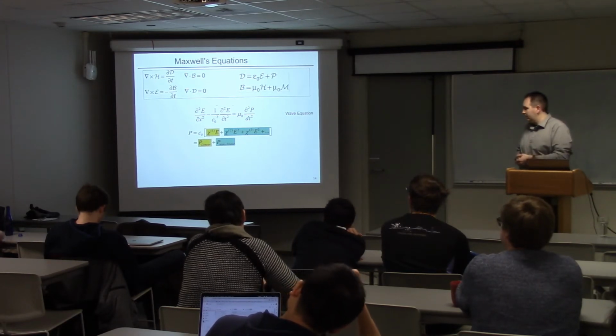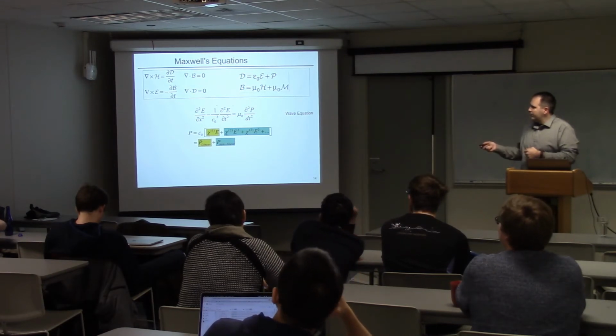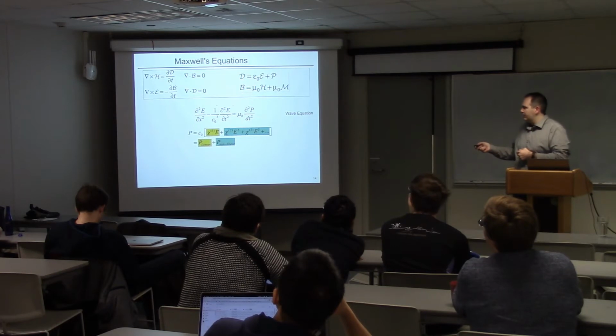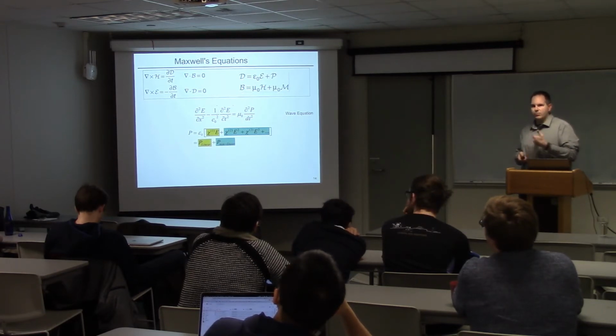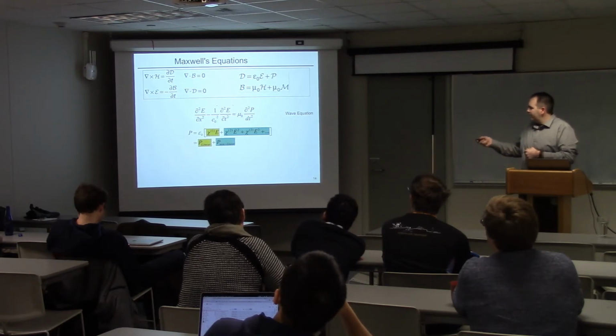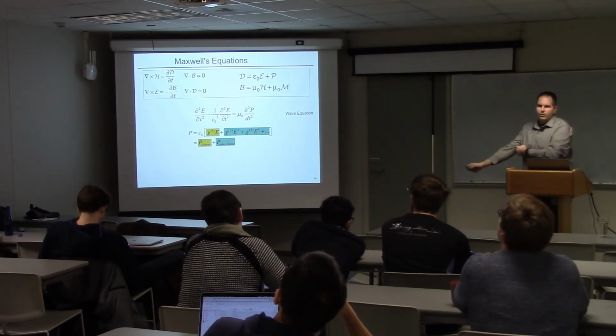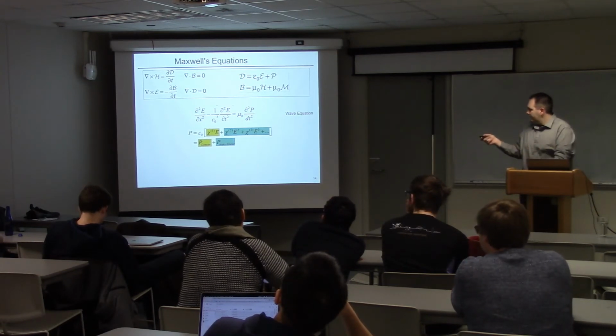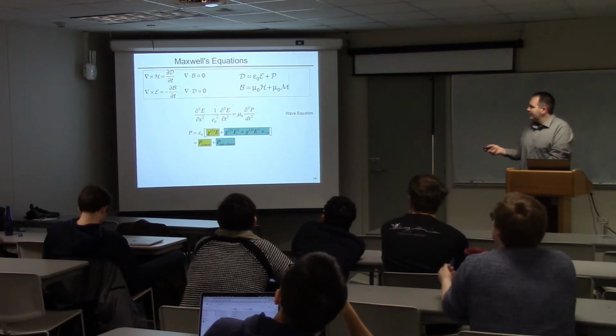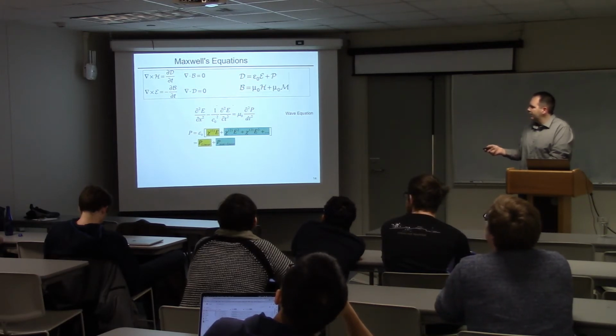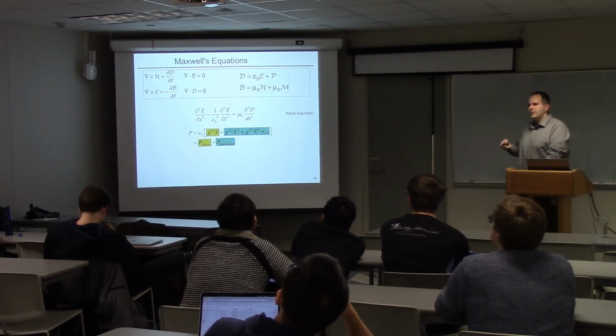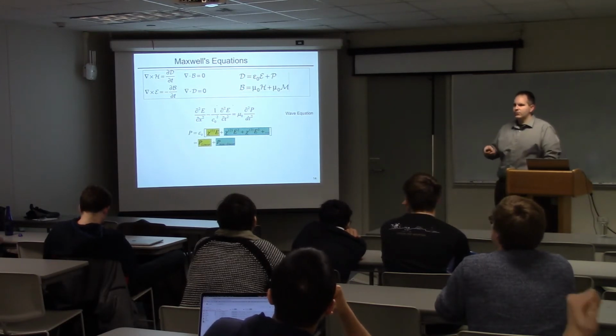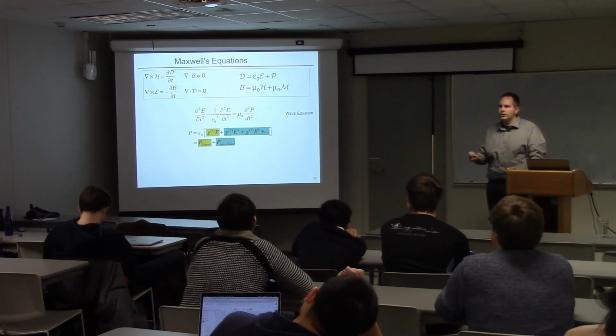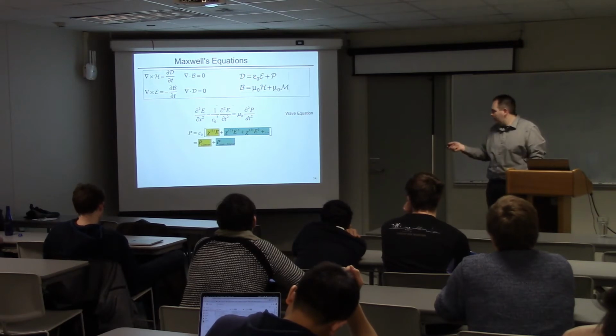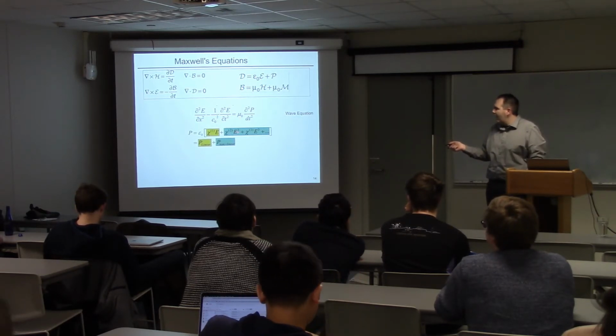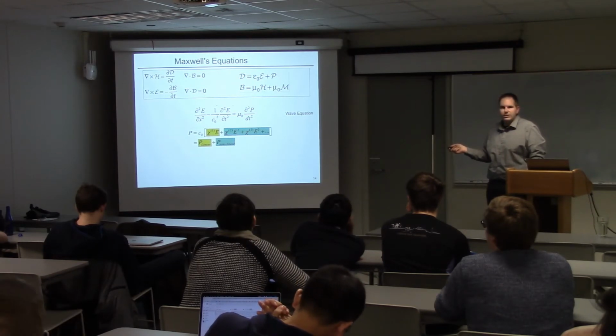electrical and magnetic fields. If you take the curl of this equation here, you can derive the wave equation. And this wave equation governs how electromagnetic radiation propagates in a media. On the right-hand side, you have this term, P, which is the polarization density in the equation. Normally, in a lot of classical introductory physics or electromagnetics, you'll stop with just this linear term. But in fact, materials have these nonlinear coefficients or terms. The materials inherently are nonlinear, but these coefficients are so small, and they're proportional to the electric fields, that unless you really have a high electric field to turn on these small coefficients, we typically don't see them.